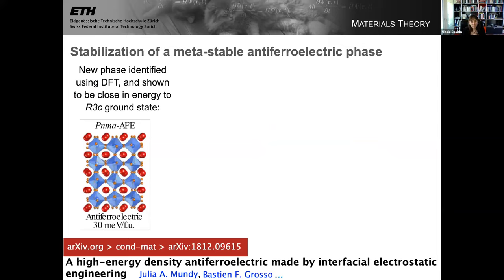And so Bastian was able to use density functional calculations to search for structures, for arrangements of the bismuth ions relative to the FeO6 octahedra in perovskite-based bismuth ferrite that were, of course, higher in energy than the ground state, but not too high in energy. And he was able to identify a new phase, which had not previously been considered, which is PNMA symmetry, and has this anti-ferroelectric pattern of the bismuth. You don't see it so well from this orientation, but it's two up, two down, then a layer where they're all the same, and then two down, two up, and so on. And this was only 30 millielectron volts per formula unit above the R3C ground state, the usual ferroelectric ground state.